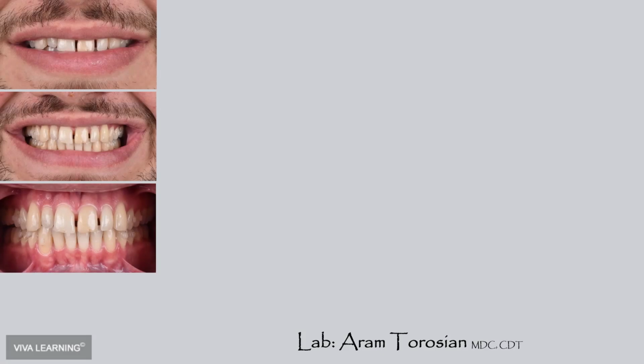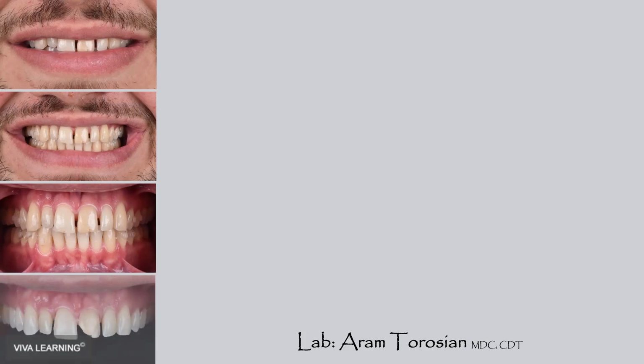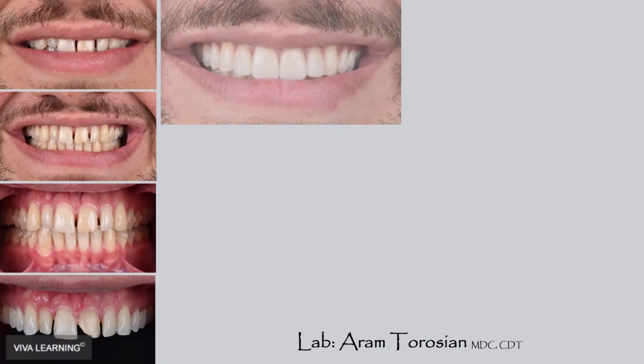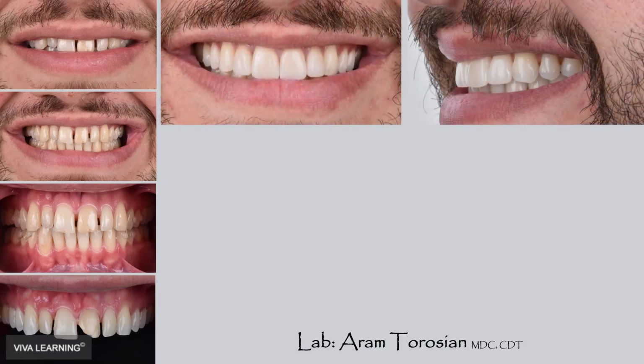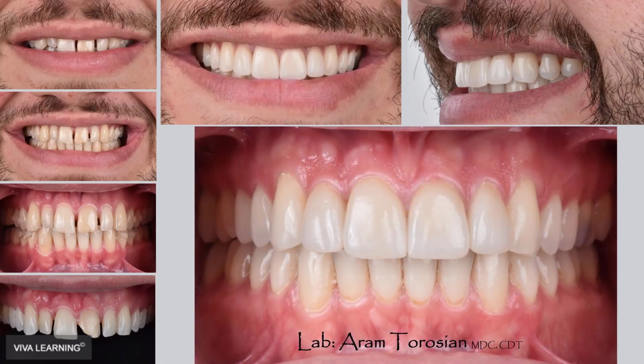Now, if you take a look at that case, by using a B05 and having a very talented lab tech, we can see that we were able to achieve very nice aesthetic results. We do have a nice blending of the 4 incisor veneers to the rest of the dentition. And choosing the right material, a lithium disilicate veneer, plus the right cement, Panavia Veneer LC, did the magic here.